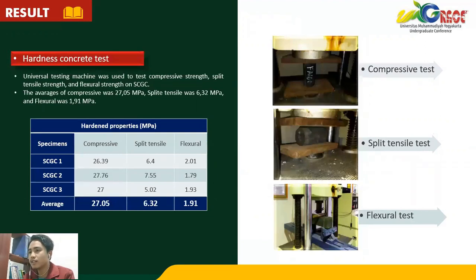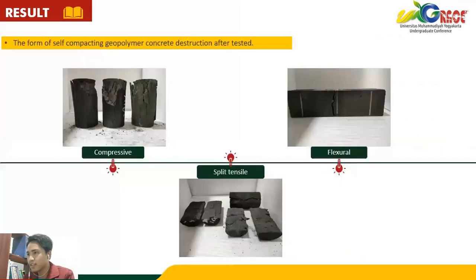And for the hardened concrete test, we used a universal testing machine. The averages were: compressive strength 27 MPa, split tensile 6.32 MPa, and flexural 1.9 MPa. So this is the form of the self-compacting geopolymer concrete destruction after being tested.